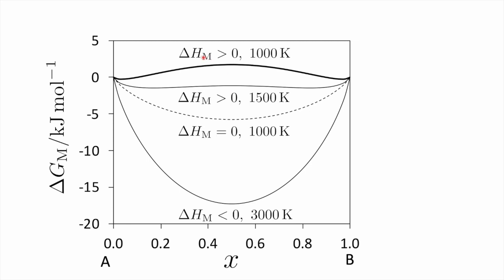On the other hand, if the enthalpy of mixing is greater than zero, which effectively means that the atoms prefer to be next to their own kind, then you get minima at the A-rich and the B-rich locations. So the atoms will tend to cluster into A-rich and B-rich regions. And there is a role of temperature, because temperature doesn't like this kind of separation of atoms. If the temperature increases, then the minima get much, much smaller, and eventually you get complete mixing, rather like this curve. So temperature favors the mixing of everything, even if the enthalpy change is greater than zero. In other words, it opposes the clustering of atoms.